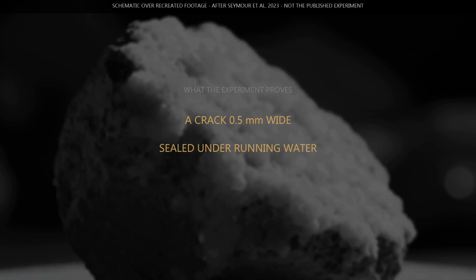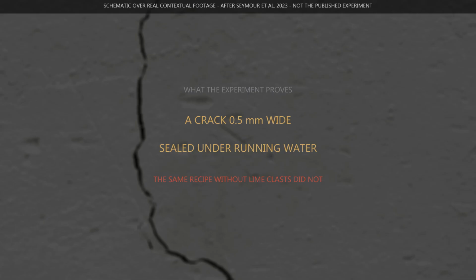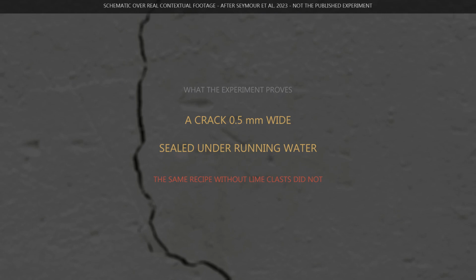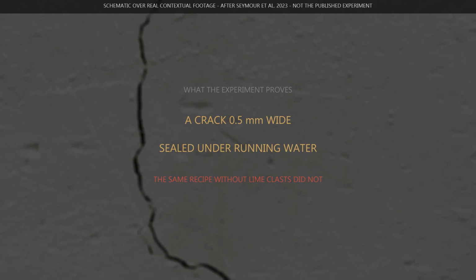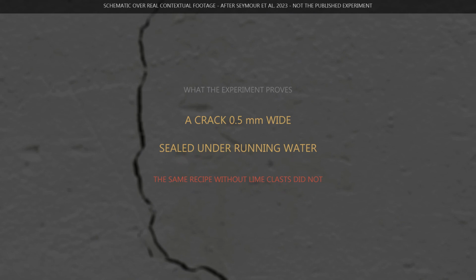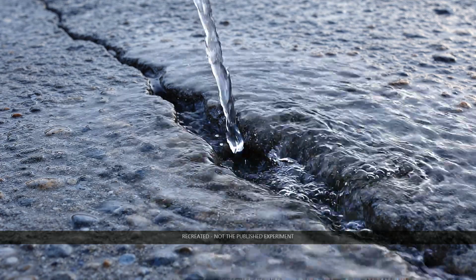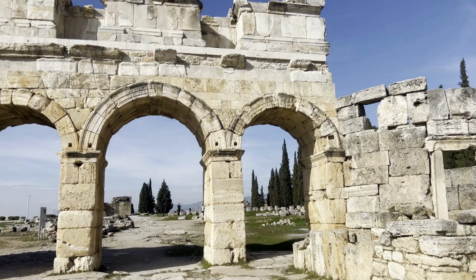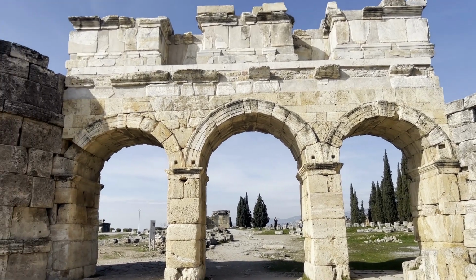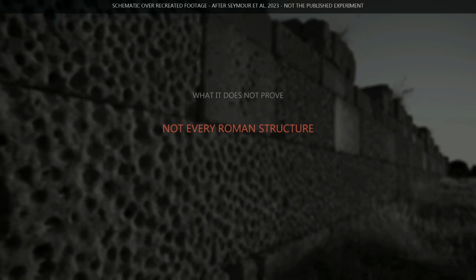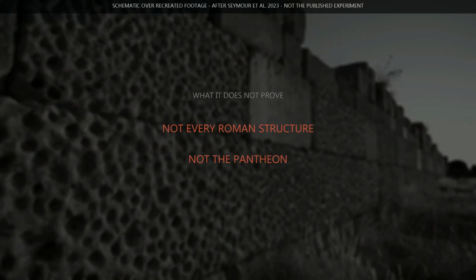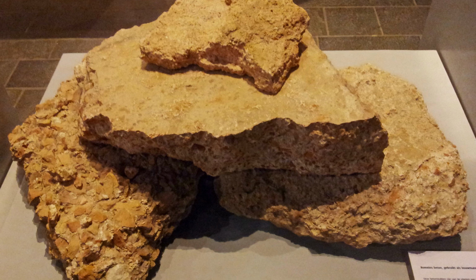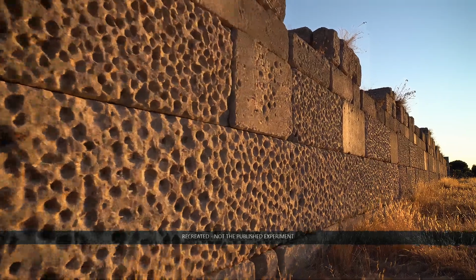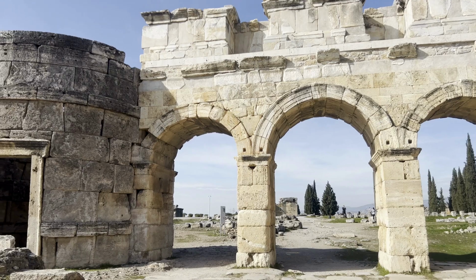Now, what this proves and what it does not. It proves that a hot mixed concrete carrying lime clasts can seal a crack 0.5 millimetre wide under running water, and that the same recipe without them cannot. It does not prove that every Roman structure worked this way. It does not prove the Pantheon has healed itself, and it does not tell us whether the Romans understood any of the chemistry or simply knew what lasted. Did they know?